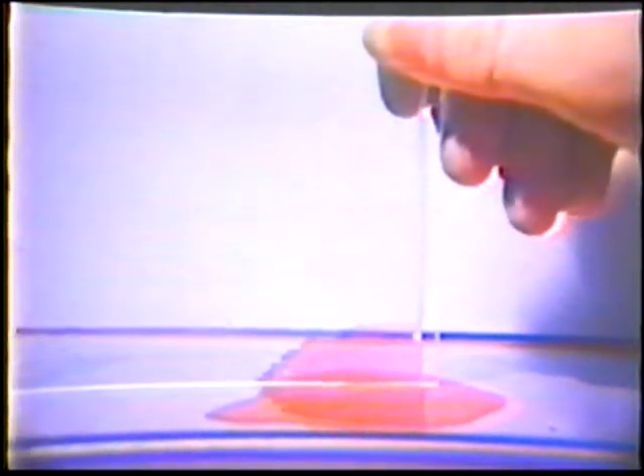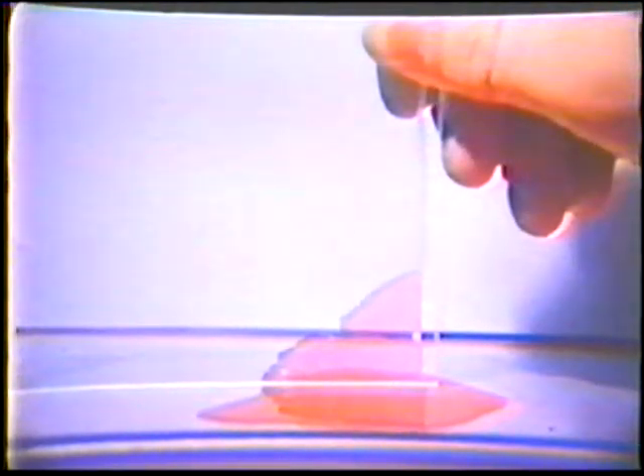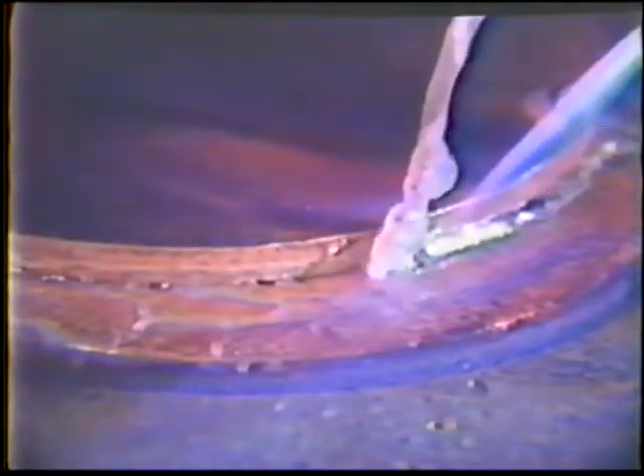The brazing of a joint this thin depends on capillary attraction, the tendency for liquids to spread out between closely spaced materials. We can demonstrate this with 2 pieces of glass spaced about 1/1000th of an inch along one edge and about 10/1000ths inch along the opposite edge. If we dip the edges in colored ink, we see that the ink rises highly in a very thinly spaced area and only a smaller amount in the wider spaced area. When 2 pieces of cleaned and fluxed metal are placed tightly together and heated to the proper temperature, the filler metal will flow into the space just as the ink did, as seen here in slow motion.